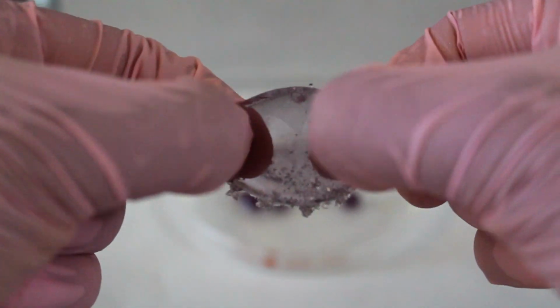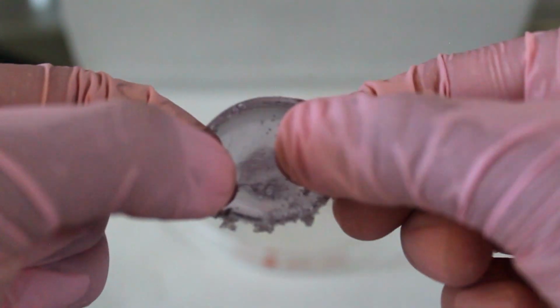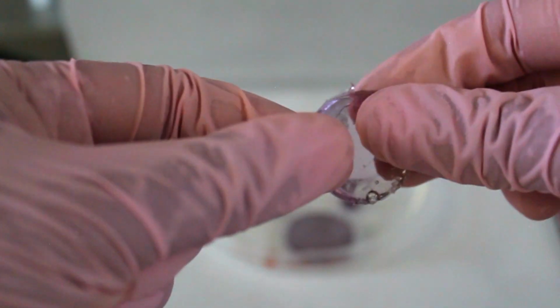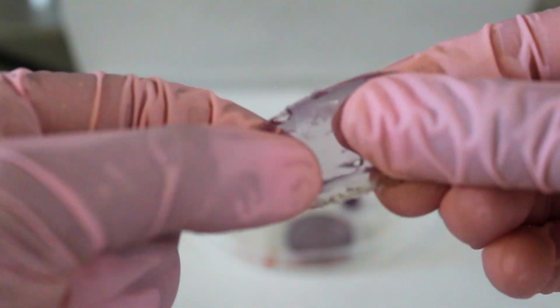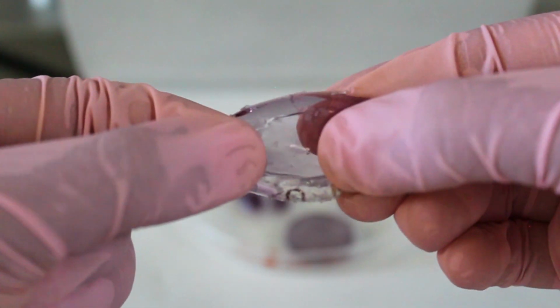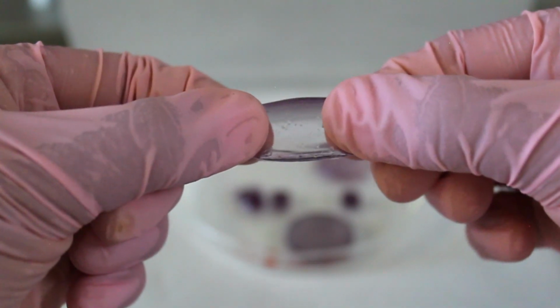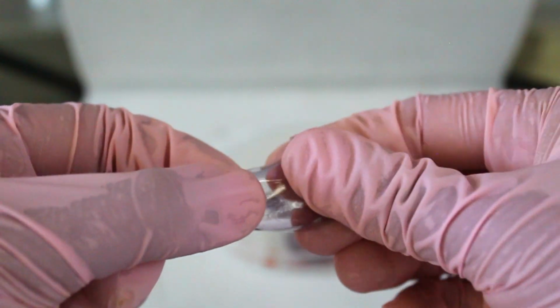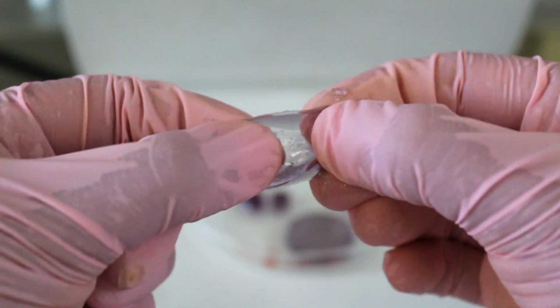The eutectogel was made possible by adding gelatin to the gold colloid at high temperature and cooling down the solution to promote gelation, and trapping of the gold nanoparticles and the deep eutectic solvent into the polymer network. These findings mark the beginning of potential ionotronic materials with plasmonic responses for greener, flexible electronics devices.